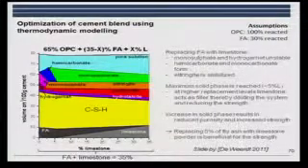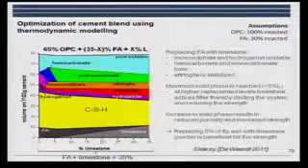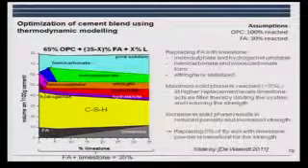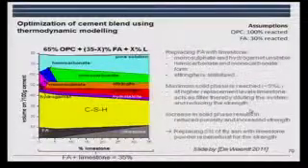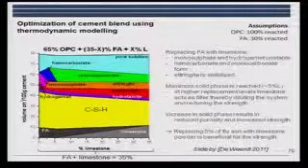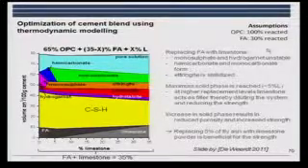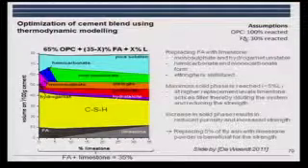And what they found with these materials they were looking at, this Portland cement, this fly ash, was that with 5% of limestone, they got the best mix. In this, you have to make some assumptions, and one of the most important is the degree of reaction of the materials. So, questions?